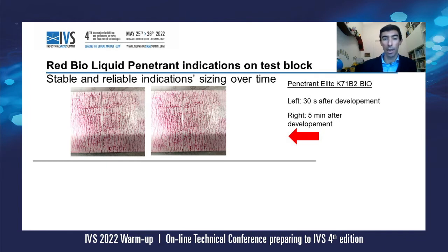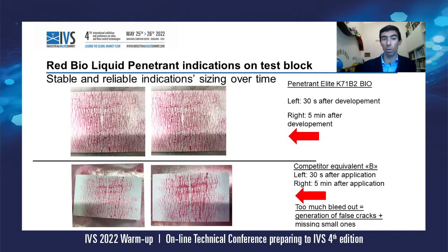We have the comparison here below with another product from a competitor, equivalent but not bio, oil-based, and you see clearly the difference. On the left, small cracks indicated, but after some minutes, the bleed out, meaning the penetrant coming out of the crack, is so much that you risk to overestimate the size of some crack, as well as missing the very small one on the side. So it's important to have a stable indication as shown with Elite penetrants.